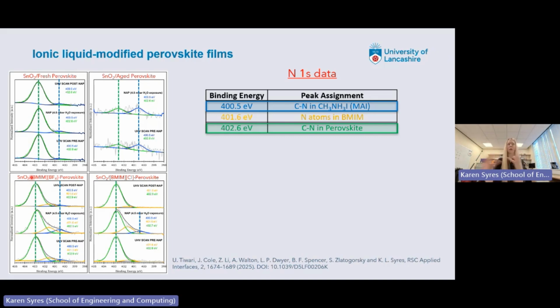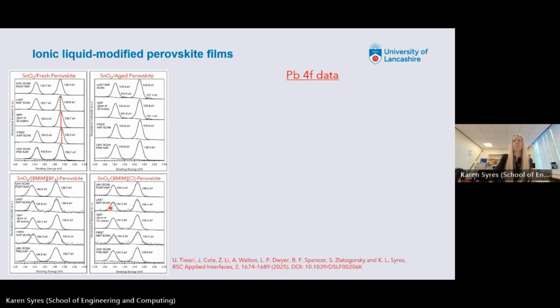So there might be some rearrangement going on of the structure as we put the water in. But when we pump it back out, it actually just seems to go back to how it was. So there didn't seem to be any particular damage to it whilst we exposed it to water. So what we see is that the ionic liquids protect our perovskite from degradation.